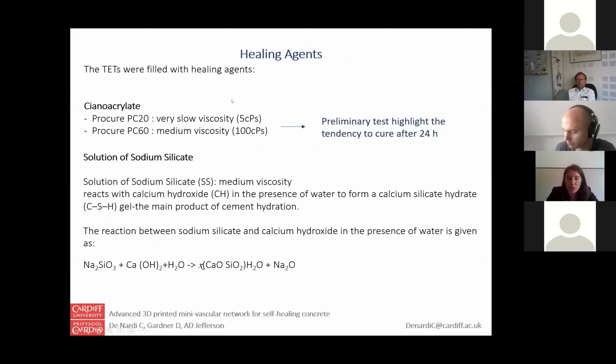Well, as the healing agents, we at the beginning started to use super glue. So we tested a lot of types of cyanoacrylates, but unfortunately, preliminary tests highlighted the tendency to cure after 24 hours. So we moved on to the use of sodium silicate, which is widely studied in self-healing concrete because it has a medium-low viscosity. It reacts easily with the calcium hydroxide present in Portland cement, in the presence of water, to form the calcium silicate hydrate gel, which is the main product of cement hydration.